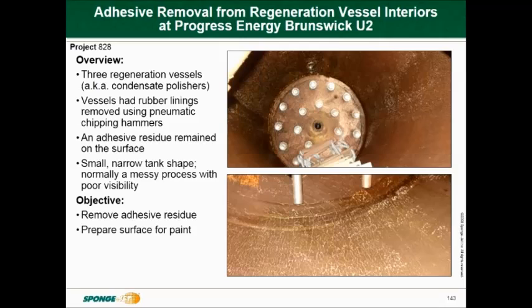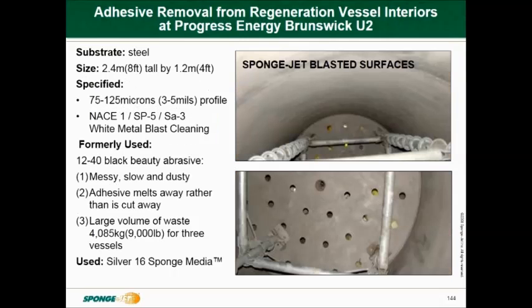Project 828, a regeneration vessel, AKA a condensate polisher. It had a rubber lining in it, and it was removed with SpongeJet, to remove an adhesive compound that was left on the substrate and to prepare it for a new coating on the inside. Normally they would use copper slag on this particular application, which they would use 9,000 pounds on 3 vessels. That's 3,000 pounds per vessel, or 1,361 kilograms of copper slag. Silver sponge media 16 was used in its place, and this tile shows the breakdown and the costs, and more importantly the saving.